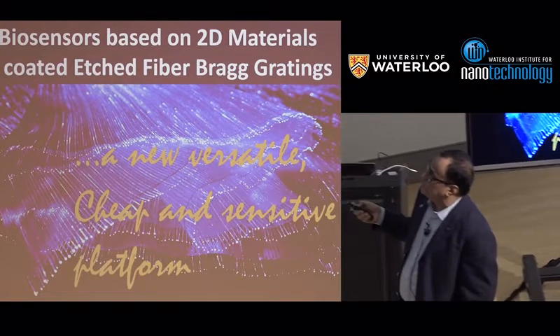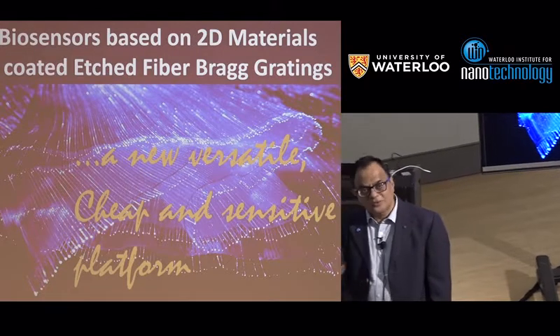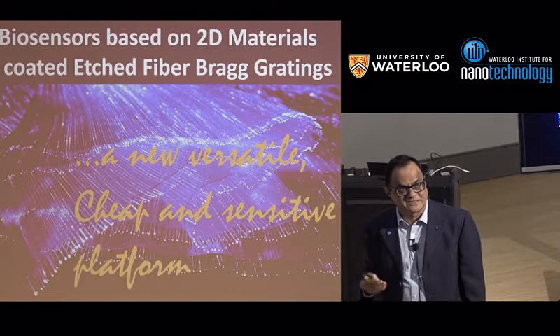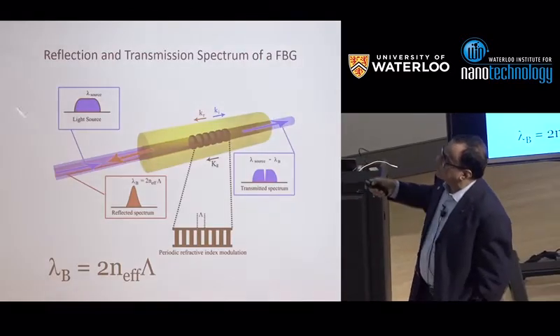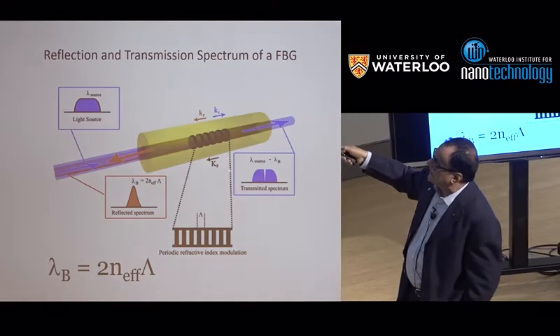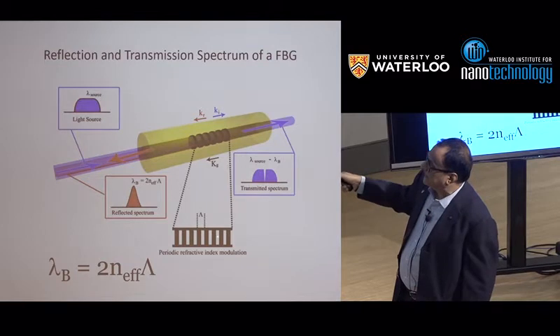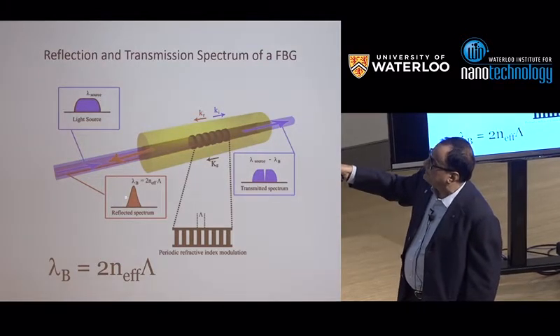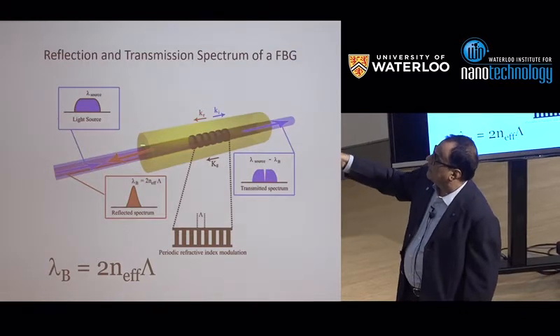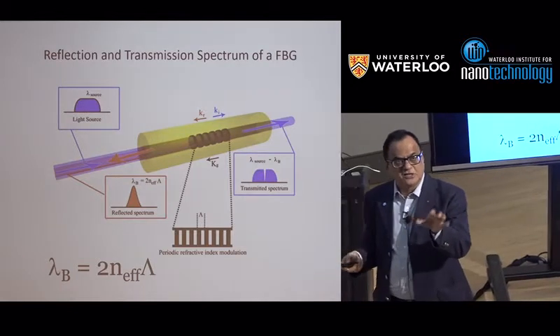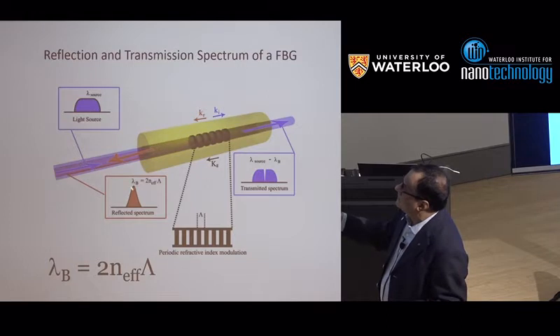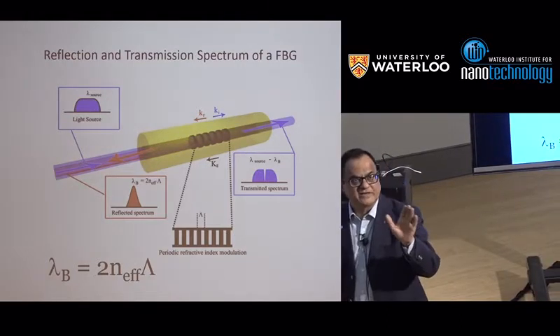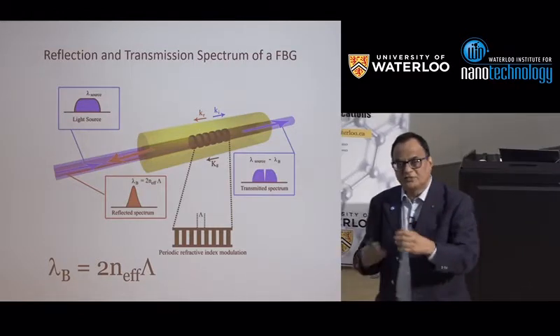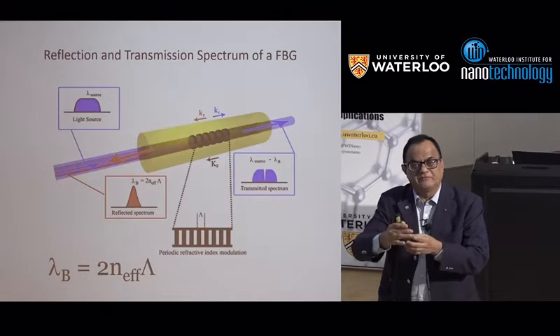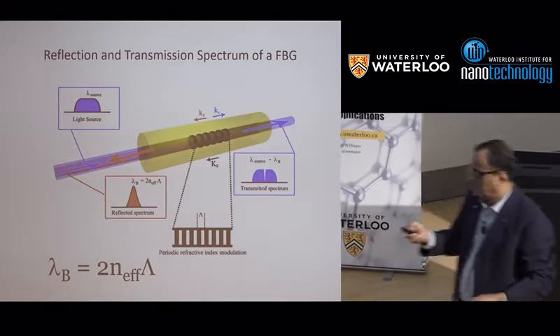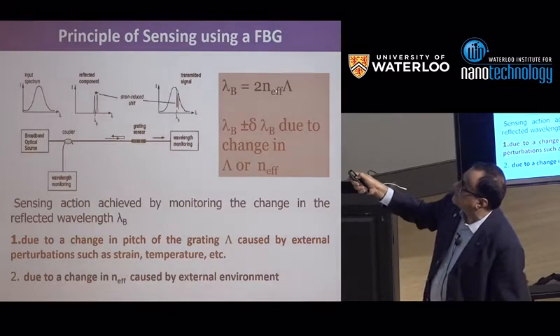So what we have shown is, you take the fiber Bragg gratings and use them as sensors for biological sensors or chemical sensors. So what is the idea here? The idea is that when you take a fiber and you write a grating with a UV light, you know the pitch of the grating, and when you put light here, only one wavelength depending on this Bragg condition will be reflected and others will be transmitted. So experimentally what you can measure is this Bragg wavelength, which is lambda b. Very simple, and this is at the heart of smart materials which people put in buildings. You put this fiber Bragg grating, and if the building has some issues, then this lambda b will shift because the grating spacing will change, which is lambda.